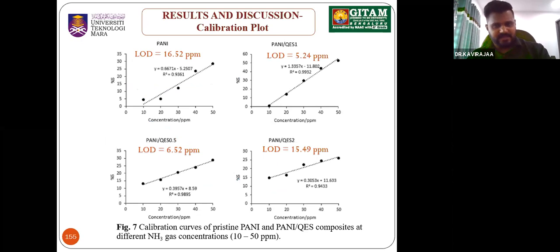We started this work with the calibration plot. We tested the calibration for the pristine PANI and also the composite materials. As you can see here, the PANI/QES1 exhibited the highest linearity and a correlation coefficient of 0.9932. It also recorded the lowest limit of detection, which is 5.24 ppm. So that's why we selected only this composite to carry out the other sensing properties.